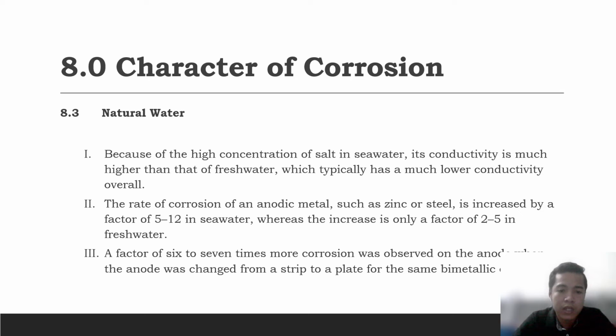So the corrosion of anodic metal such as zinc or steel increased by a factor of 5 to 12 in seawater, and in fresh water it is only a factor of 2 to 5. So we can see the conductivity in seawater is higher than in fresh water. And then next, a factor of 6 to 7 times more corrosion was observed.